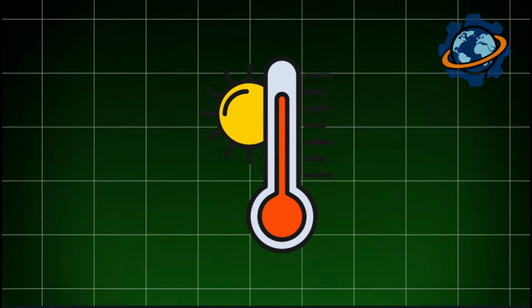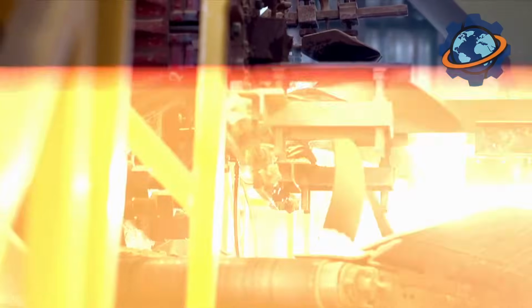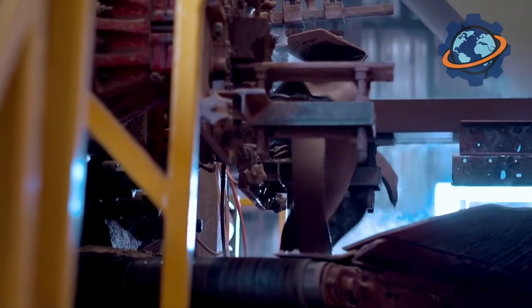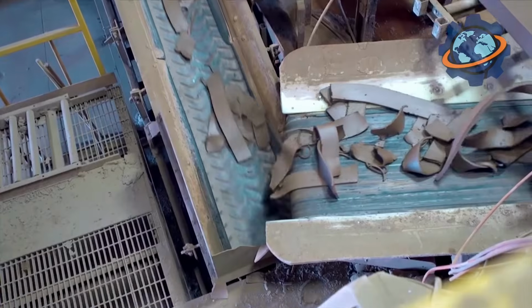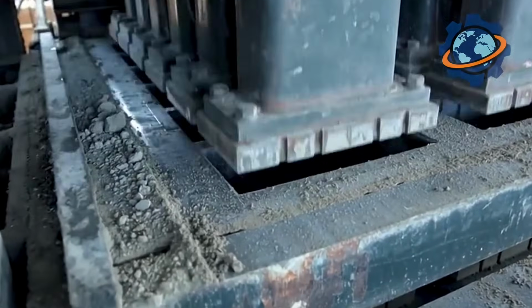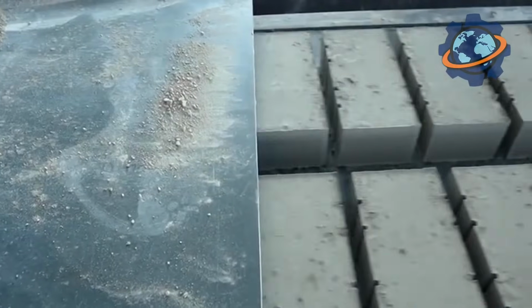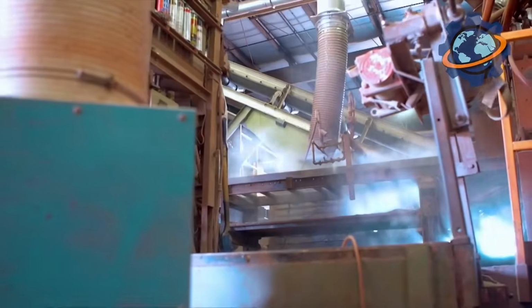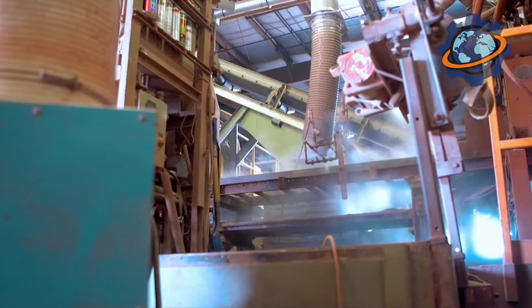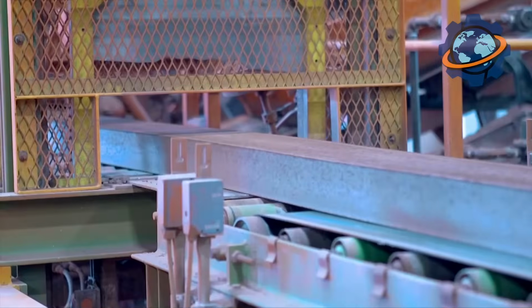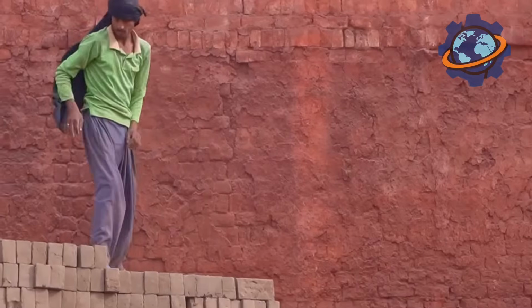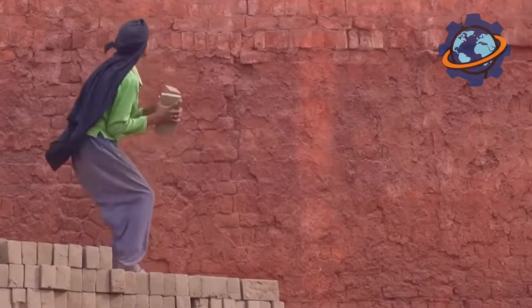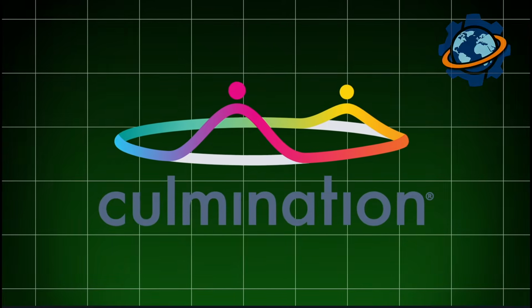It is important that the moisture leaves the brick as evenly as possible from its entire thickness. Any rush or violation of the regime will lead to the outer layers drying faster than the inner ones, which will create critical internal stresses and simply tear the brick apart with cracks from the inside. When all the physically bound water is removed, the culmination of the entire production cycle begins: firing.